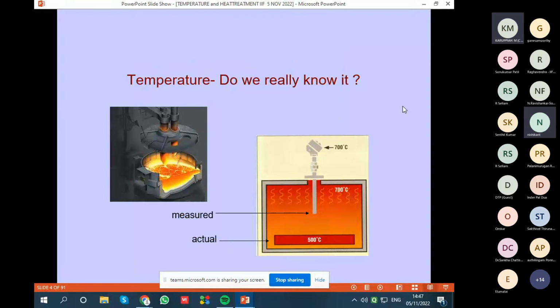This slide is very interesting because it shows a typical furnace, a bit exaggerated. The actual temperature is 500 degrees centigrade while the measurement is shown to you as 700. This is a lot of exaggeration, but this is just to drive the point home. The measurement we do in a furnace or anywhere in the plant is not necessarily the right measurement of the job. It depends on the location of the thermocouple, calibration and many factors.